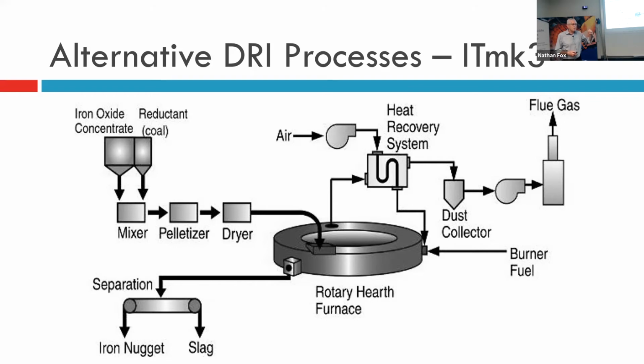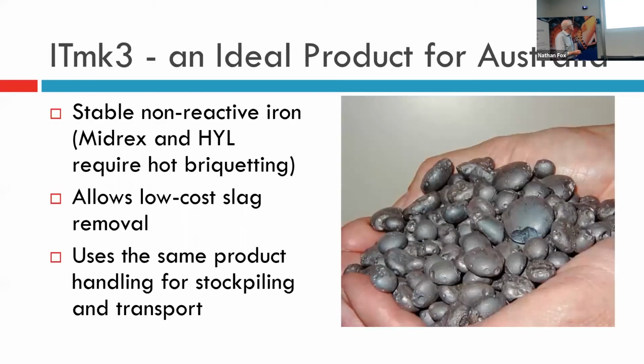It's easily transportable. It's not going to reoxidize again. And any slag that you've got, any impurities that are in the iron oxide, form a slag, and that can actually be easily separated because it seems to coalesce separate to the iron. It forms this stable product, so there's no need for the hot briquetting side of it. And it also allows a low-cost removal of slag.